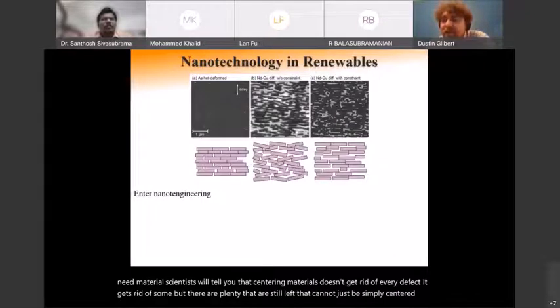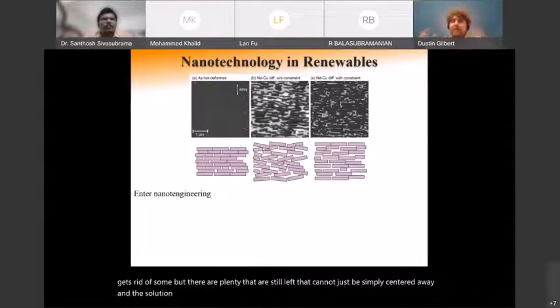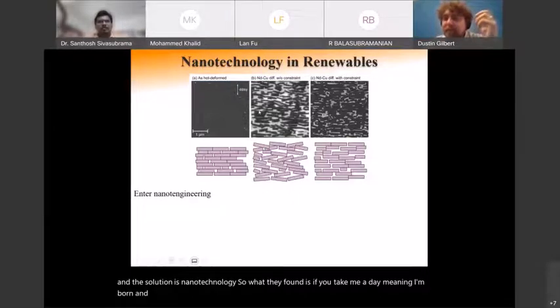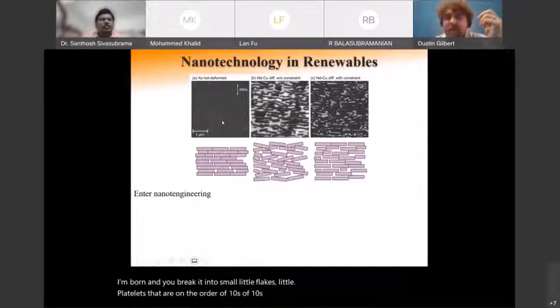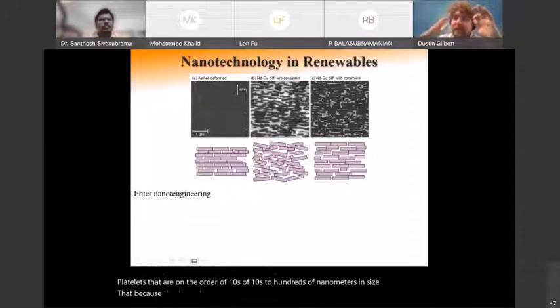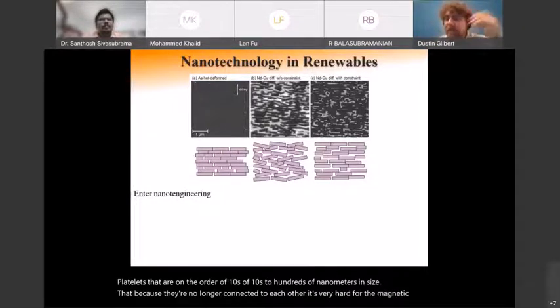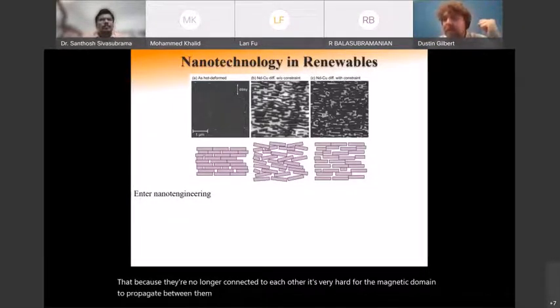And the solution is nanotechnology. So what they found is if you take neodymium iron boron and you break it into small little flakes, little platelets that are on the order of tens to hundreds of nanometers in size, because they're no longer connected to each other, it's very hard for the magnetic domain to propagate between them. This significantly improved the magnet, but we can still make it better.